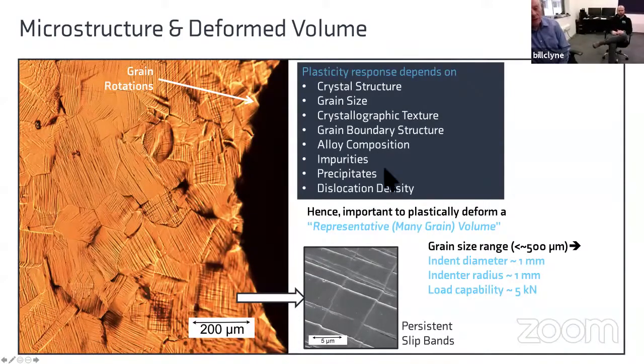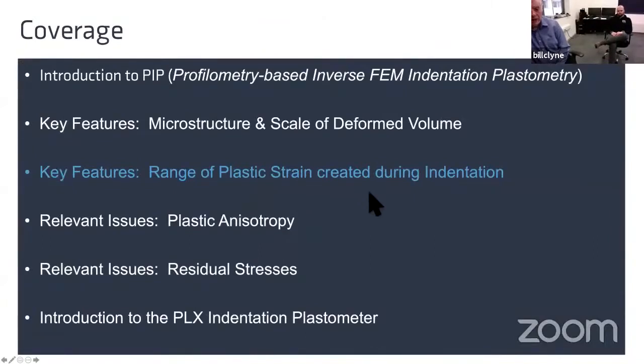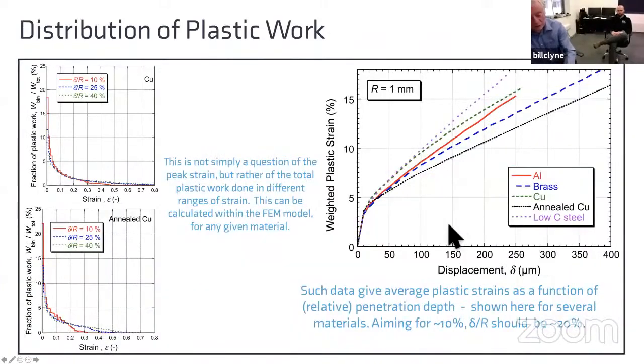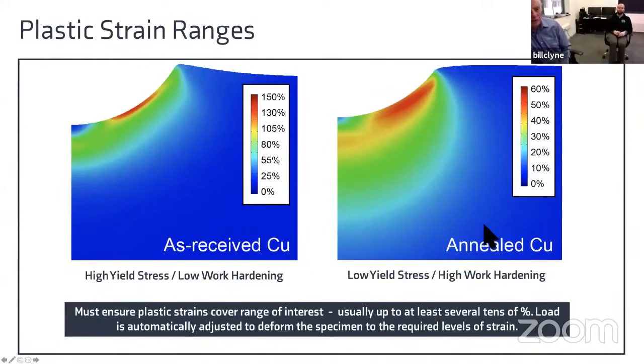There's other issues. One of them is what kind of plastic strain do you create during the process? You obviously need to create a relatively large range of plastic strain. If you're trying to capture how the material responds during a typical tensile test or something like that, you need to be going up to tens of percent typically. If you've only created plastic strains of a few percent, you're not going to capture the response over the right sort of range. Now, the plastic strain range depends on a lot of things, but obviously it depends on how deeply you're going relative to the indenter radius.